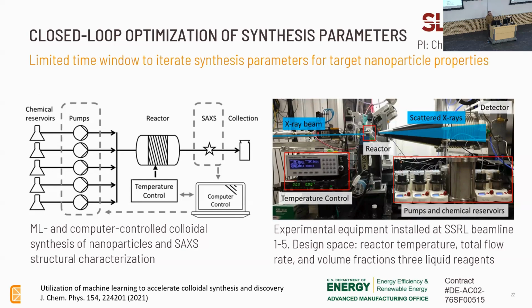So the challenge was they wanted to very rapidly test a set of knobs on these reactors, make the nanoparticles, characterize them, and then take the results of that characterization and immediately make more particles and do it again until they could figure out the optimum way of doing it. So they had to do all this in real time while they had access to the beamline. And that's exactly where machine learning can help.